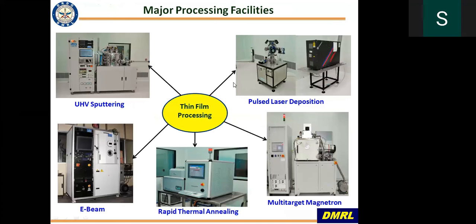These are some of the facilities we have in our laboratory. We have an ultra high vacuum sputtering system, pulsed laser deposition, and electron beam. We have rapid thermal annealing and multi-target sputtering, and we use different kinds of techniques. If it is an oxide, we use oxide film deposition. For tunnel junctions, we use the ultra high vacuum system. For thicker films, you go for electron beam metallization. To avoid cross contamination and other issues, we use different kinds of processing facilities in our laboratory.